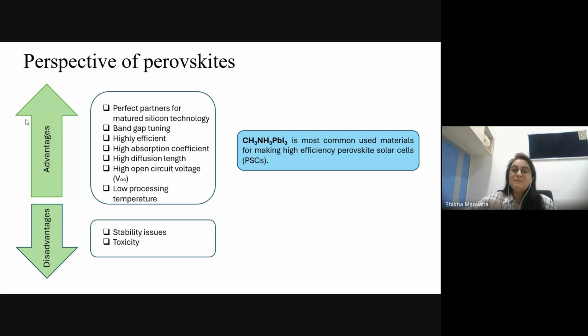Another thing is band gap tuning. As I have said, depending upon their different stoichiometric, substoichiometric coefficients, depending upon their different layers, we can tune the band gap. Highly efficient, as I've already said, in the last decade only, we have obtained a very good efficiency. So yes, they are quite efficient. High absorption coefficient, so their absorption coefficient is also quite high. They have a high diffusion length and high open circuit voltage. Another thing is they have low processing temperature.